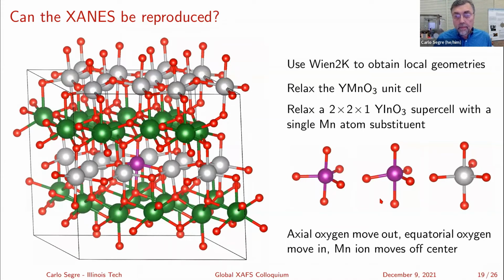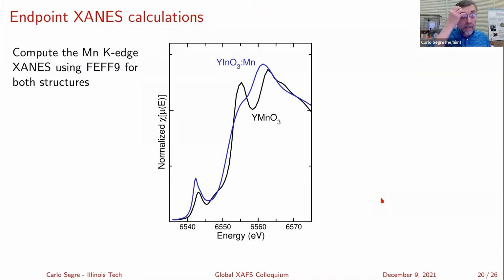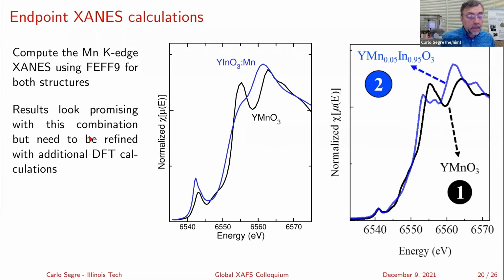So I then took FEFF9 and took the results of these VASP relaxed structures, and I calculated the XANES for the yttrium manganese O3 and the manganese doped into yttrium indium O3. Again, blue being the blue color and the black being the black color. And then I compared them to the data that we had actually obtained from the two endpoints.